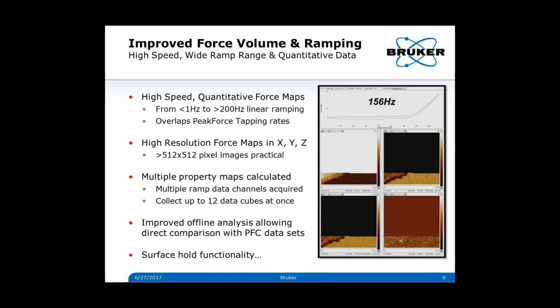And this really makes it practical to do very high resolution imaging in force volume, even greater than 512 by 512 image maps. We can also collect all the standard property channels, things like adhesion, modulus, stiffness. They're all calculated on the fly in real time, and we can get up to 12 data cubes. The raw data is all saved, so that's great. We improved the offline analysis to allow direct comparison with peak force capture or peak force tapping data. And we also have a surface hold functionality, which we'll be talking about more with regard to the contact resonance.